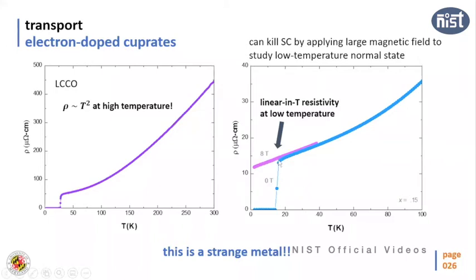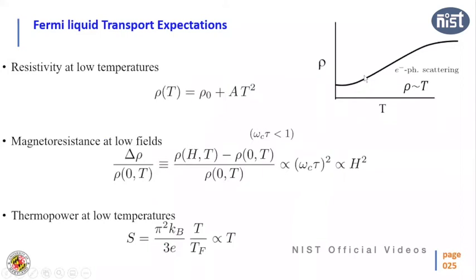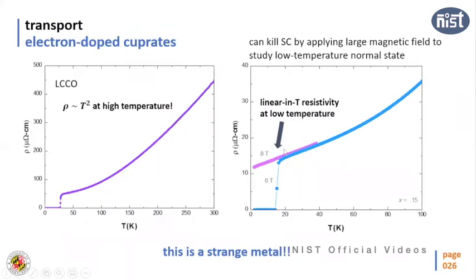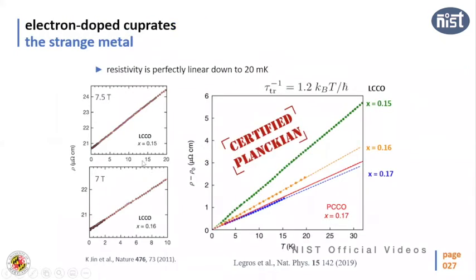And not only that, this blue one is a superconductor. It has TC around 15 Kelvin. Now, if we apply magnetic field around 8 Tesla, we can restore the resistive state. So this is the resistive state. What happens? This resistivity as a function of temperature shows linear behavior. As we have seen in normal metal, there would be some kind of saturation and also a bend. It should follow this kind of T square behavior. Instead of doing that, it shows linear behavior, and that linearity was measured down to 20 millikelvin. This work was published from this Maryland group, from our group, in Nature.